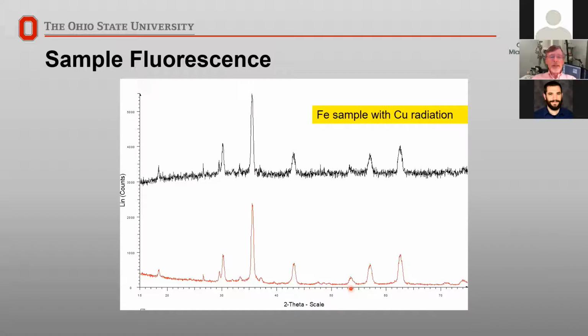So for example, this peak here is just barely visible in the unfiltered scan, and you miss these 3 peaks right here that are quite visible in this scan. So this is primarily a problem with the elements just below copper in the periodic table. So cobalt, iron, manganese, chrome tend to have a lot of fluorescence. So in our SmartLab, we do have a monochromator. We can minimize this effect.